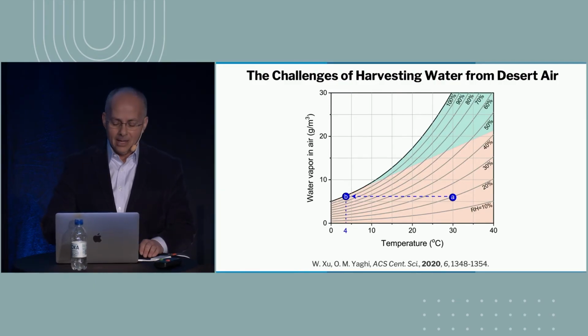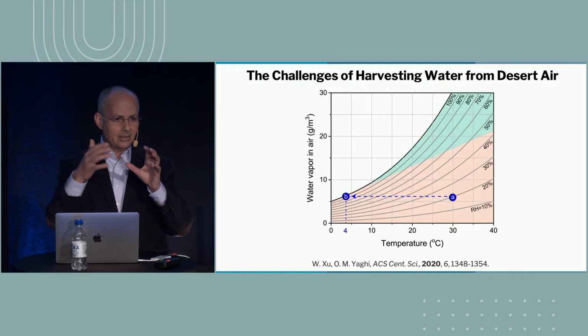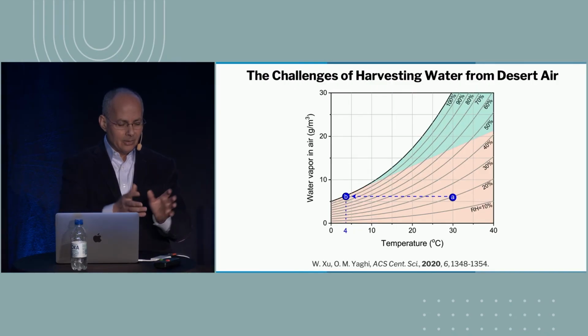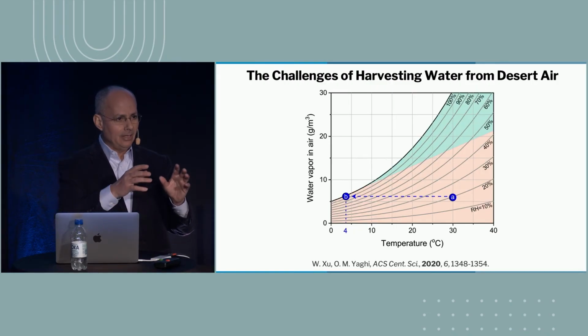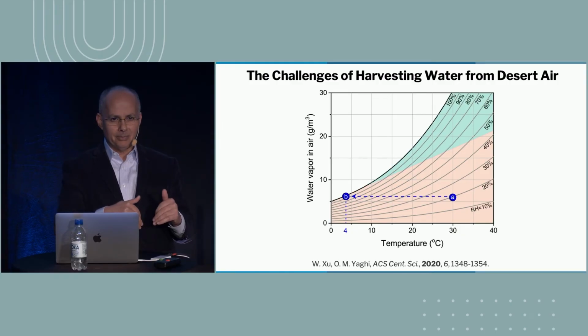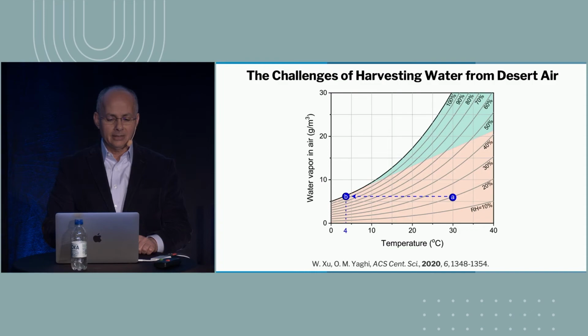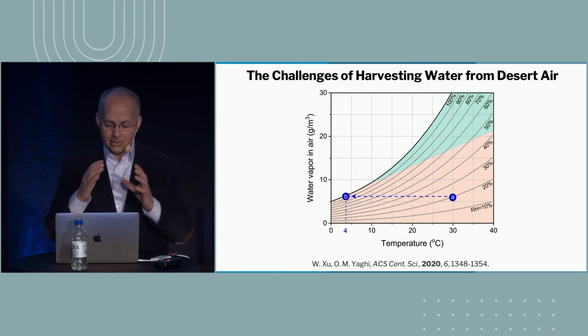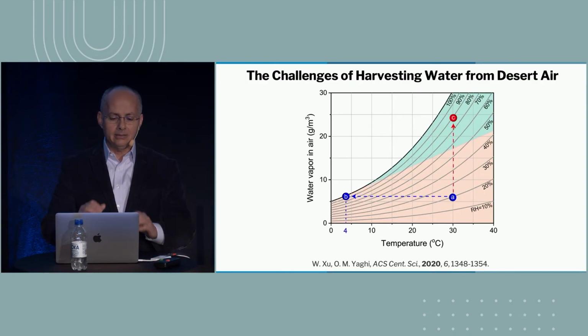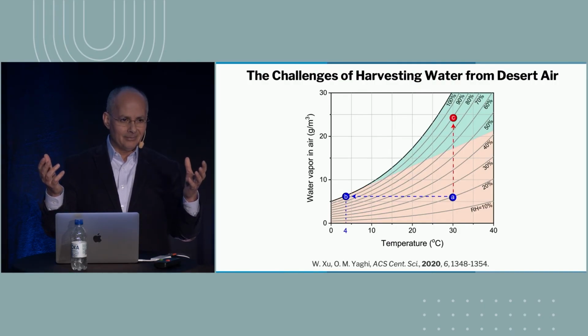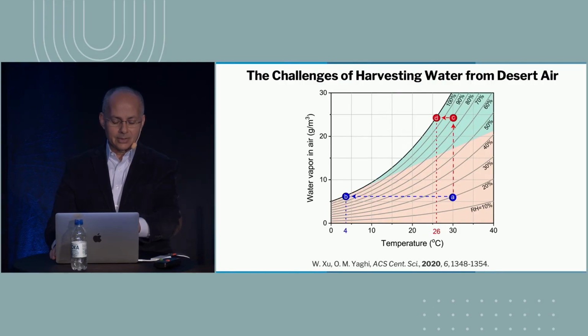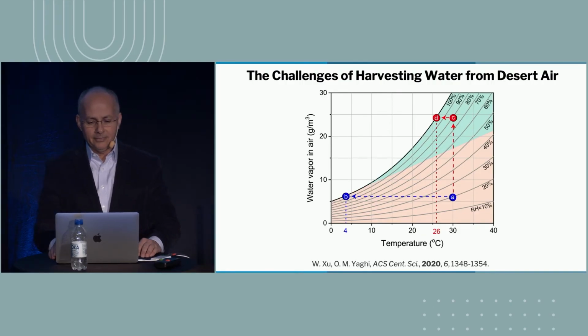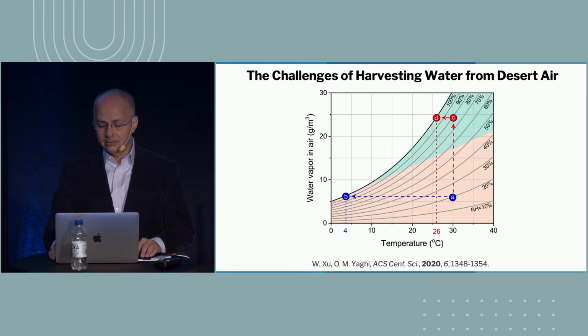Okay, that's very energy intensive. However, if I have a MOF that plucks water out of the air and concentrates it in its pores, I can put it in a box, close that box, and expose it to the sunlight. The sunlight heats up the box, and water comes out of the MOF and condenses. Because the MOF can concentrate water into the pores, I can increase the humidity inside that box to 90%. I can take desert air and make it tropical air. And to get water out of tropical air doesn't take much. You only have to reduce the temperature by 4 degrees in this case to get the water out.